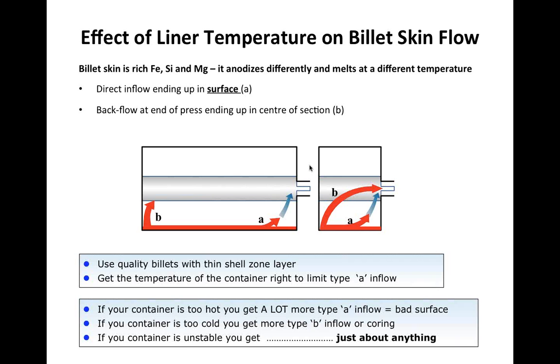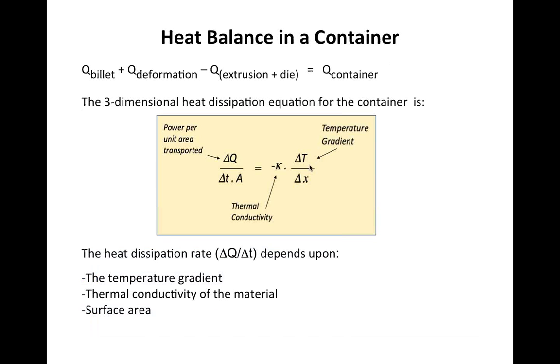type B inflow. What's more interesting is when I go to extruders and ask, do you know what your liner temperature is? Most of the time, or 95% of the time, they do not know. They only know the reading from the thermocouples. So anything can happen in their container because the container temperature or liner temperature is not stable. Typically the thermocouple reading only tells us the minimum temperature. If you set the thermocouple in your container at say 800 or 820 degrees, below a billet temperature which may be 860 degrees, the only thing that thermocouple does is turn the heaters on when the container is less than 800 or 820 degrees. There's no control whatsoever at temperatures above that.